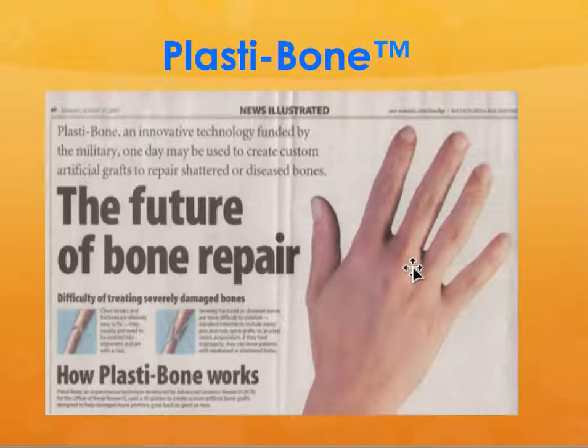One of the things that I did a couple of years ago was that you heard about different kinds of implants. The most common implant is made out of titanium or stainless steel. What is the disadvantage with those kinds of metals? The problem is that those metals are much stronger and harder than our natural bone, and they do not have the same inner structure like our bone. So what they can do is they can break off small pieces of our bone during the time it is implanted into our body, and it can break away and chip away. So if you have an implant today, after about 10 to 15 years, you will have to go for a revision surgery and put in a bigger implant into that same place.